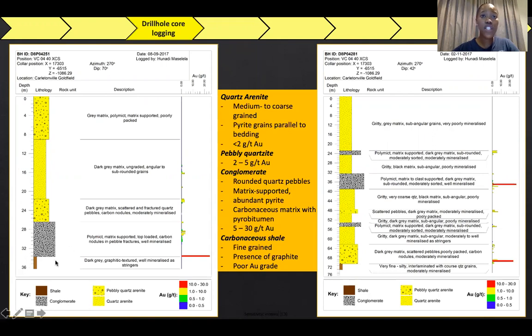They are interbedded with well-packed, matrix-supported conglomerate units. The gold concentration in these units ranges from 5 to 30 grams per ton in some instances, and the quartz pebbles are often embedded in a black carbonaceous matrix with abundant pyrobitumen, which frequently occurs at the bottom contacts. These conglomerate units eventually grade down to a carbonaceous shale with rounded pyrite nodules and pyrite orientated as stringers. In places, the carbonaceous shale is intercalated with gold-rich conglomerates, and these carbonaceous shales contain graphite in the matrix.